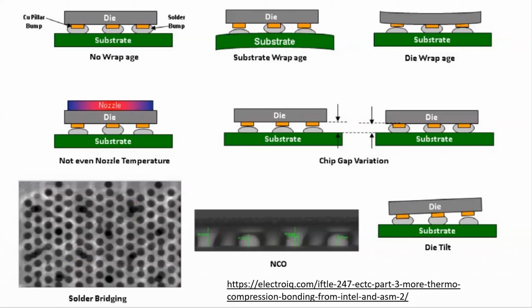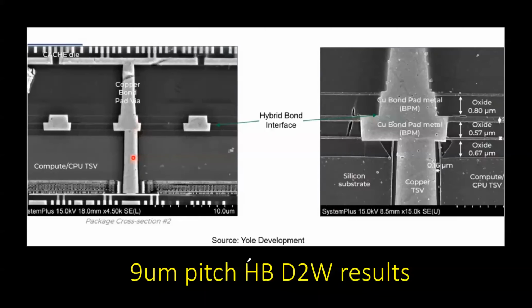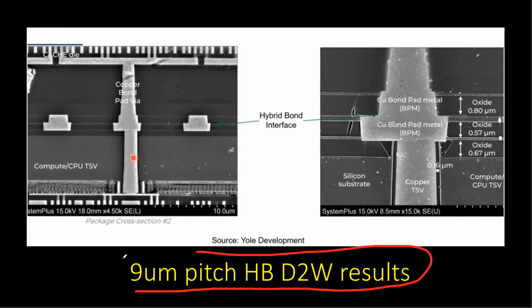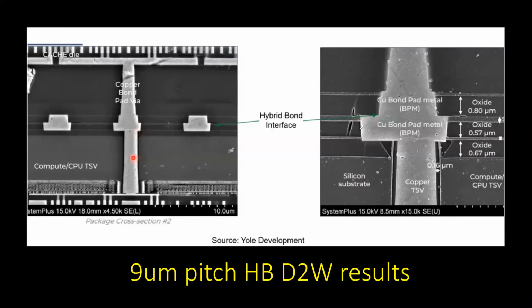That's also bad. But currently, Yole, this consulting company, shows that the hybrid bonding interface at 9 micron pitch has been done very nicely. Die to wafer bonding, okay, they call it HB D2W data, so there's no problem. So people seem to do 9 micron okay, especially TSMC, okay.